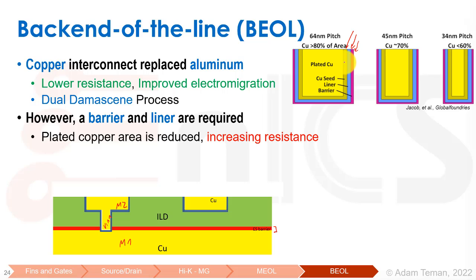So these three layers, the problem with them is they're really small and they don't scale. When we scale the interconnect layer, so we get better lithography, and we go from a pitch that's this big to a smaller pitch and to a smaller pitch, the whole thing scales, but this threesome doesn't scale. It still takes up the same room, and it leaves us with very little material that's actually low resistive, and that's real bad because it increases the resistance of going through these metal layers.